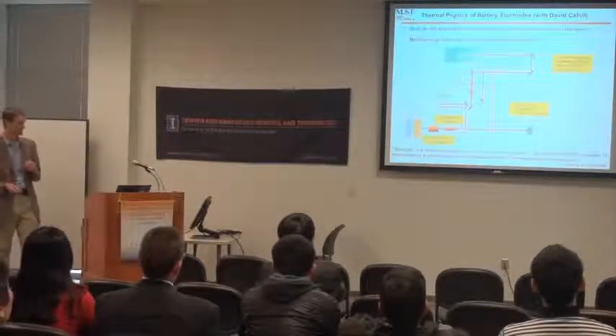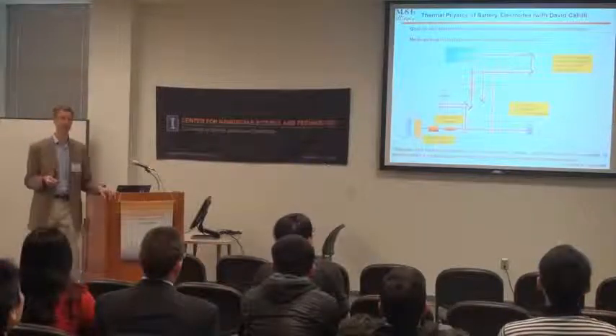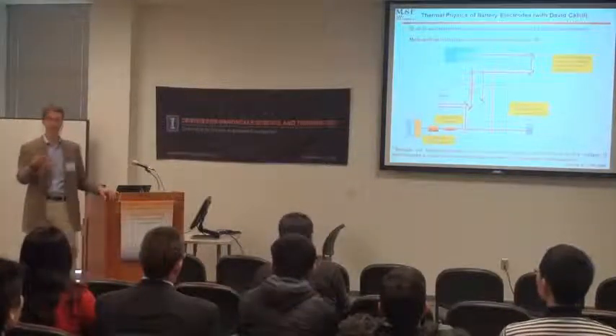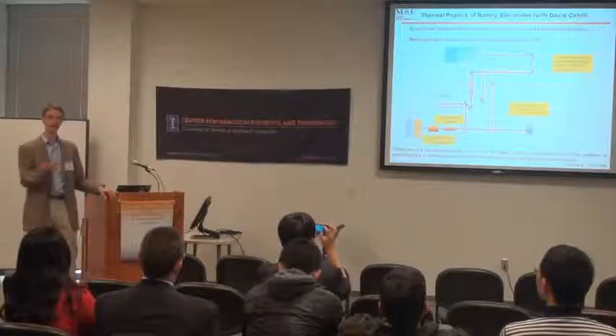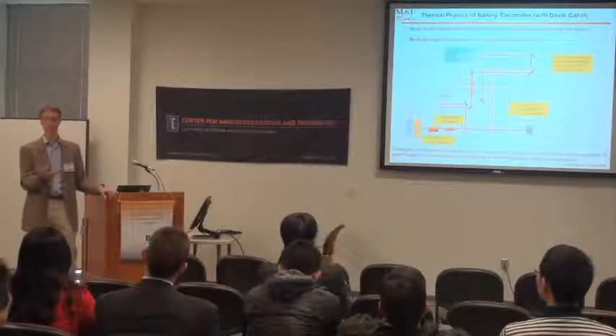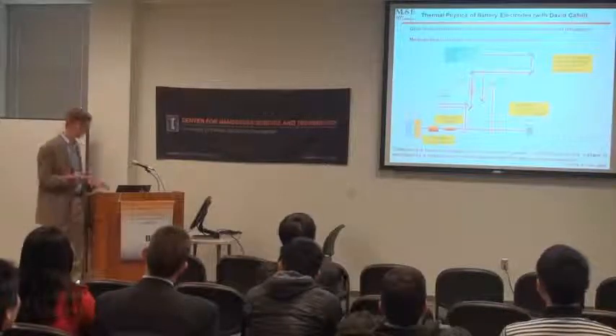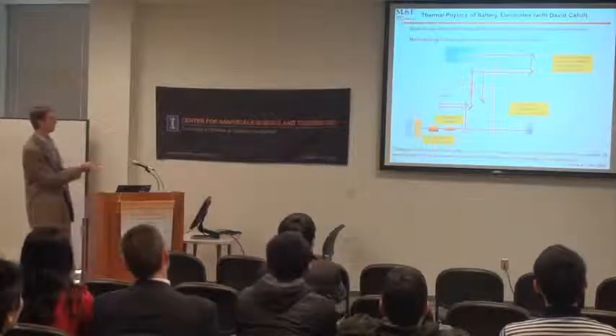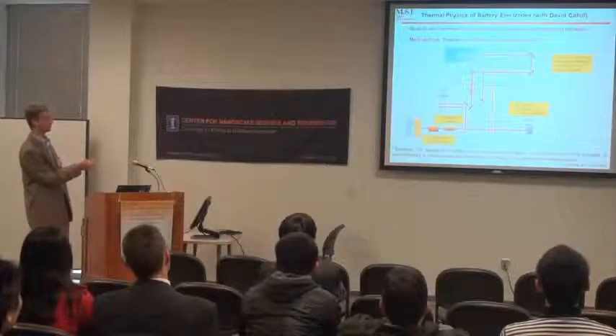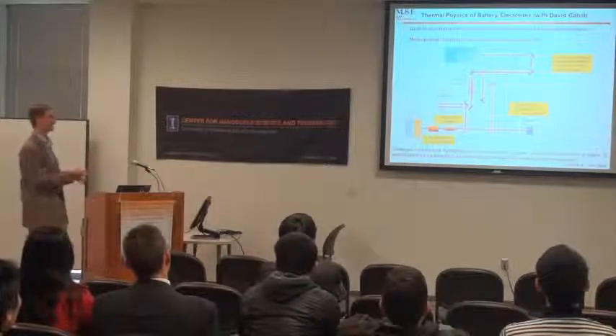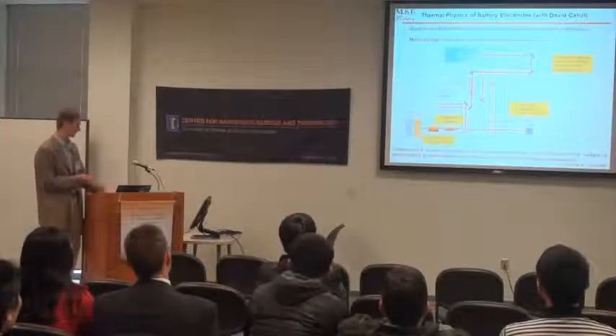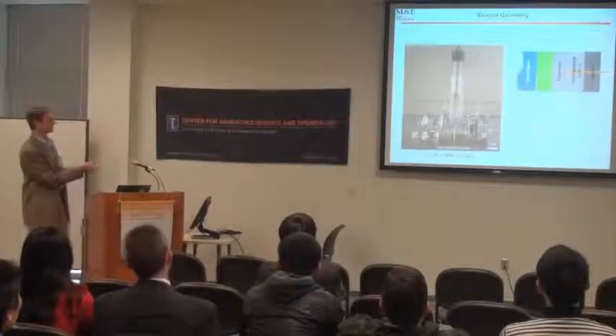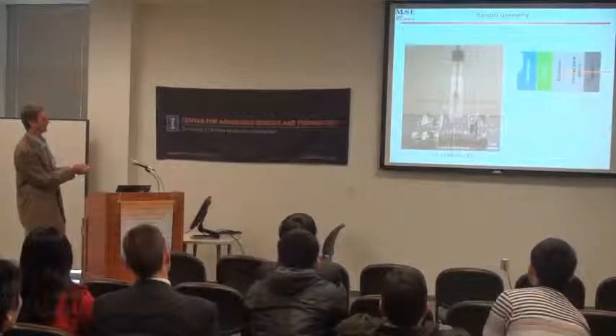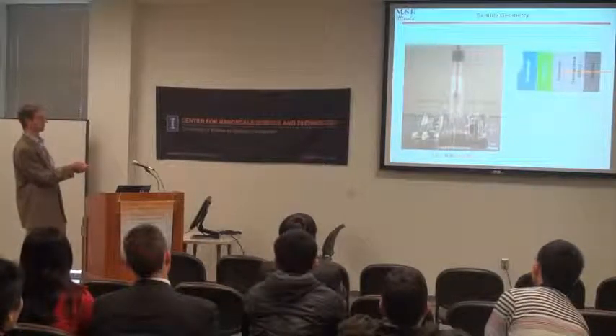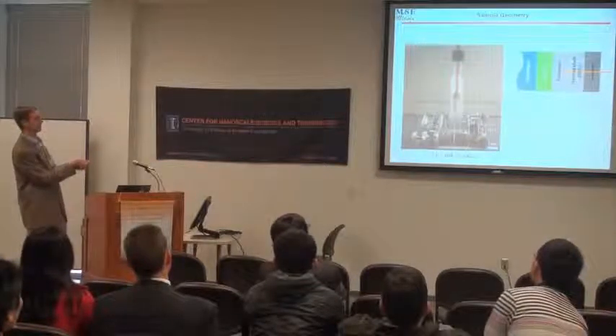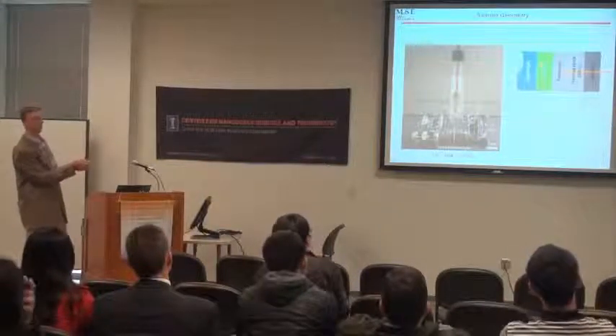So I'll just take 1 or 2 minutes here. Thermal physics in batteries matters too. If you imagine when you charge and discharge a battery, there's a lot of heat being evolved. And so we're trying to understand how the thermal properties of the constituent materials change. And it turns out that they change rather dramatically. So David has developed this wonderful technique for measuring thermal properties of thin films. I'd encourage you to just look at any number of his references for this. But basically, we build a small lithium-ion battery in a sort of non-traditional configuration, so we can bring in a laser, which we use then to measure the heat capacity and thermal conductivity of the material.